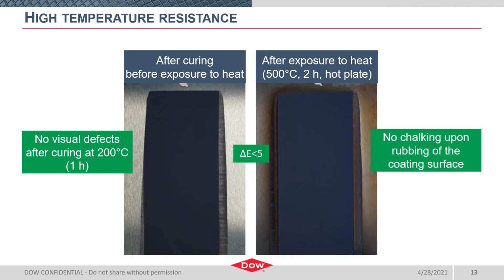This color loss is almost inevitable. It's mostly going to be from pigment oxidation and organic substituents burning off of the silicone resin. But it's very interesting to note that we actually observed the color revert closer to its initial profile once all of these organic substituents have pyrolyzed from the resin, which makes sense as degradation and organic composition can exhibit a yellow tone. When those components have all burned off as carbon dioxide and water, they're no longer there to show any discoloration or minor degradation.